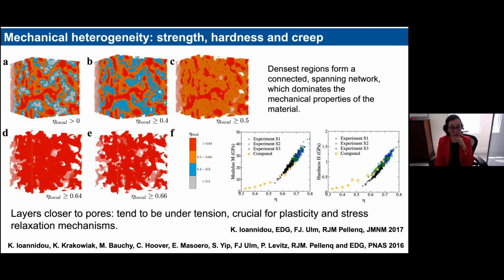You can clearly see that, in fact, this final structure of the material has this stiffer, more rigid part that is under compression, whereas the softer layers that are deposited on top during the gelation process tend to be under tension. And so you can now study how this specific sequence of internal stresses gets frozen in the material as the gelation process develops,